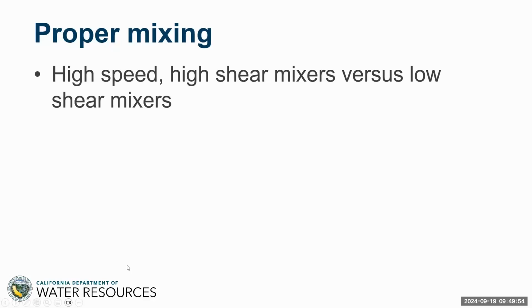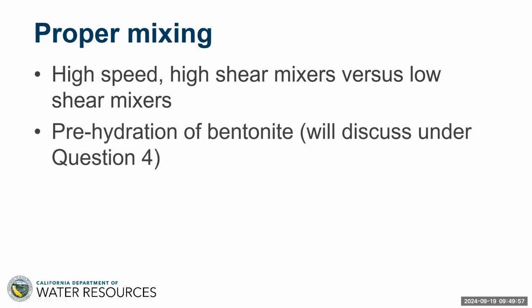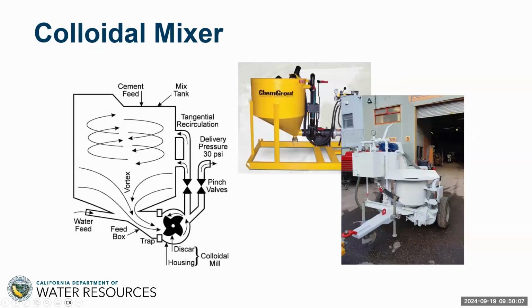High speed here, yeah, versus low shear mixers. Prehydration of bentonite is very important. We're going to discuss that later on. So what we call a high shear mixer, yeah, next slide would be fine, Julie, thank you, is shown diagrammatically on the left. The heart of a high-speed, high-shear mixer is that black star, or the disc, that's shown at the bottom there. And it spins around at maybe between 1300 and 1600 RPM inside a very tight tolerance chamber. And so the water and the cement are intimately mixed in that fashion.